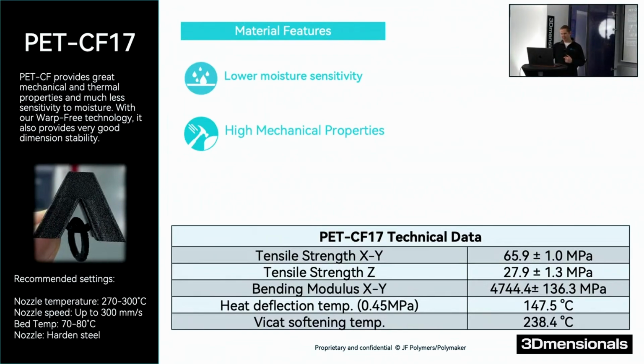PET CF17, this is a semi-crystalline polymer, performs very, very nicely, very accessible material. If the 612 is kind of the all-rounder for the nylons, I think the PET CF17 is an all-rounder for the whole of Fiberon. Very affordable and very good performance, and it prints very, very nicely. It's accessible on, I think, almost every machine nowadays will be able to print it with a nozzle temperature of 270 at the low end. You can also go a little bit higher than that.